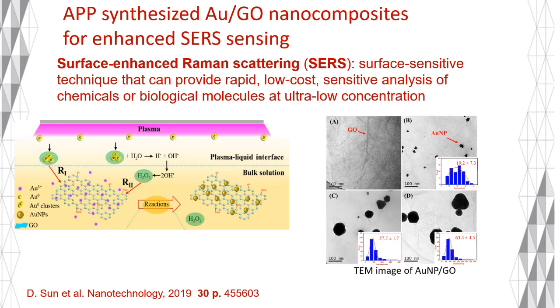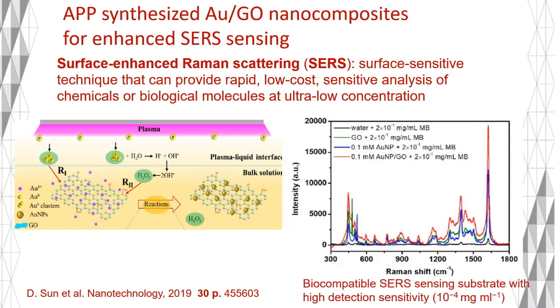As depicted in this figure, the gold and graphene oxide nanocomposite we synthesized can result in a remarkable enhancement of the Raman signal. And the detection limit reaches an impressive level of 10 to the power of minus 4 milligram per milliliter. This enables the rapid, cost-effective and sensitive analysis of chemicals for biosensing applications.